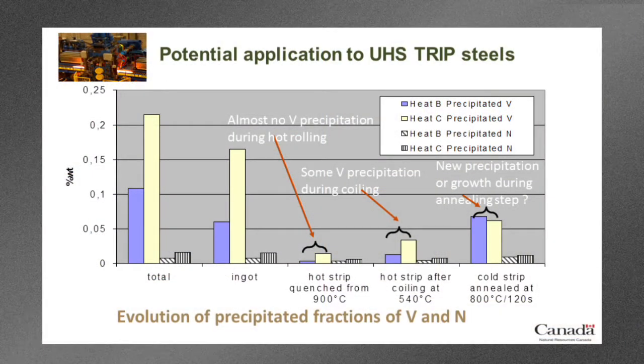First thing to do in any study like this is to say, well, what is the vanadium actually doing? When does it come out? When is it in solid solution, and when is it precipitated? So here we have, on this diagram, data taken from selective chemical dissolution experiments. What we would do is dissolve the matrix, and we can measure the amount of precipitated vanadium in any alloy at any point along the production cycle. There are two alloys on this diagram. I would really like you only to concentrate on one. This would be the blue one here, where there was 0.1 weight percent of added vanadium. So this is the total amount of vanadium that was added. Here we have the nitrogen content as well.